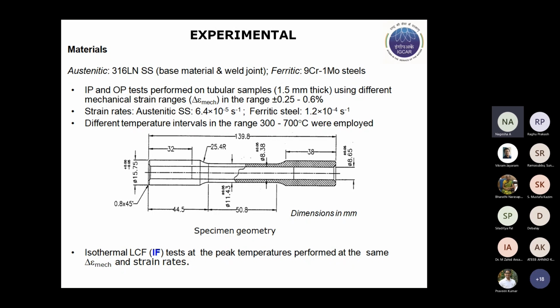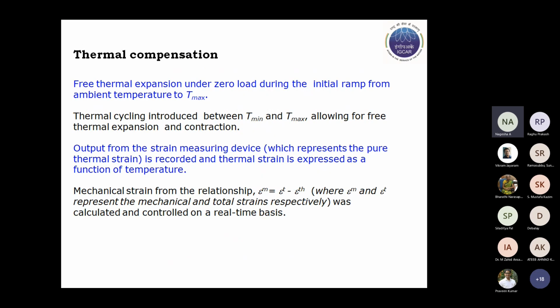Tests were carried out using temperature intervals from a minimum of 300 to a maximum of 700 degrees centigrade. And for comparison, isothermal tests were also performed at the maximum temperature of the TMF cycling, employing the same strain rate and mechanical strain amplitude. In my presentation, I will be using the term IF cycling to denote the isothermal testing. When I compare this isothermal testing, I would always compare with respect to the maximum temperature of the TMF.